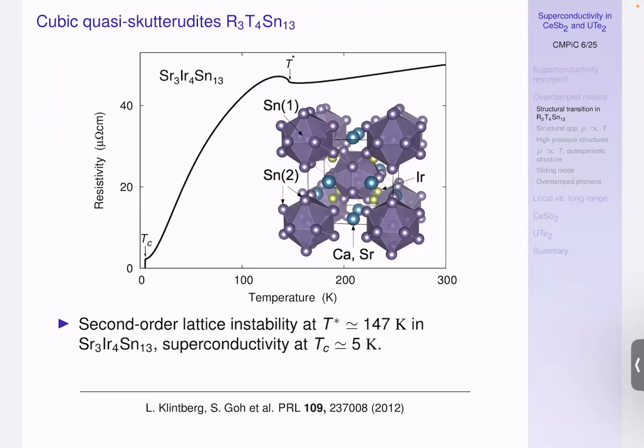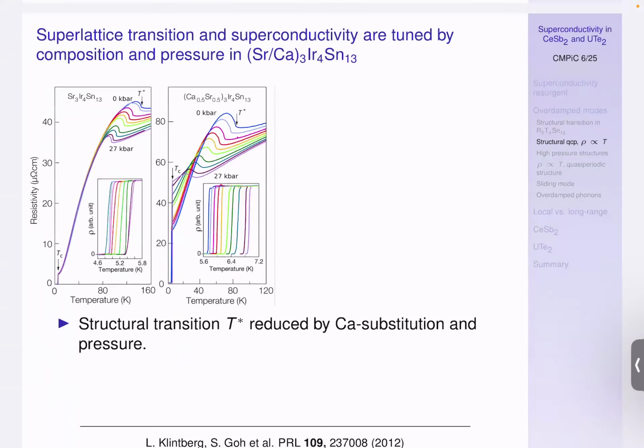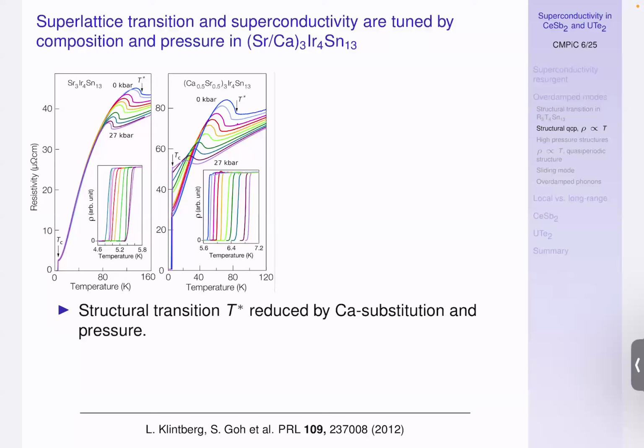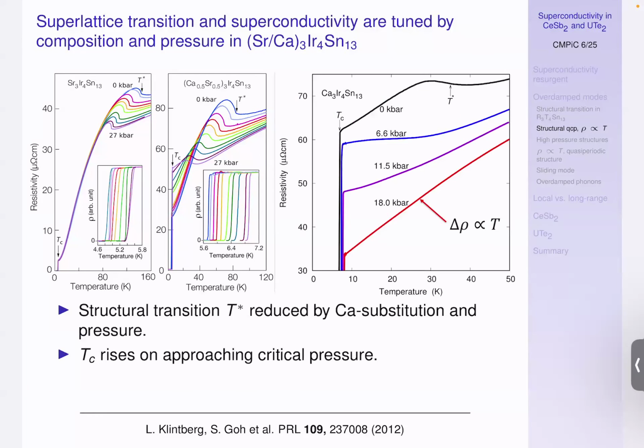So the basic idea is we're looking for materials, it doesn't matter if they look complex, materials which have a structural transition that can be tuned to zero. And in this case, in this material class here, the pnictides, 3-4-13 compounds, which by the way are also superconducting at low temperatures, that structural transition is second order. So it's a continuous phase transition. And what we found was that by either chemical pressure, i.e. replacing some of the strontium here by smaller calcium, isoelectronic substitution, or by applying hydrostatic pressure, you can suppress that structural transition gradually until it really goes away. So now you have effectively a structural critical point, if you will.